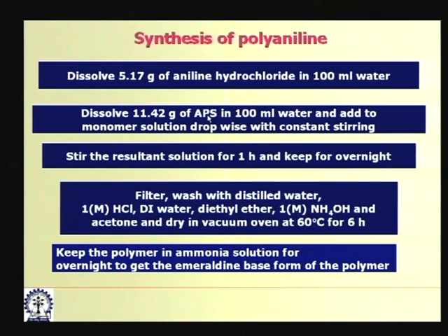11.42 grams of APS is to be dissolved in 100 milliliters of water, and then this needs to be added to this aniline hydrochloride solution dropwise with constant stirring. Since it is aniline hydrochloride, it may or may not need external acid, hydrochloric acid, because here it already contains hydrochloric acid.